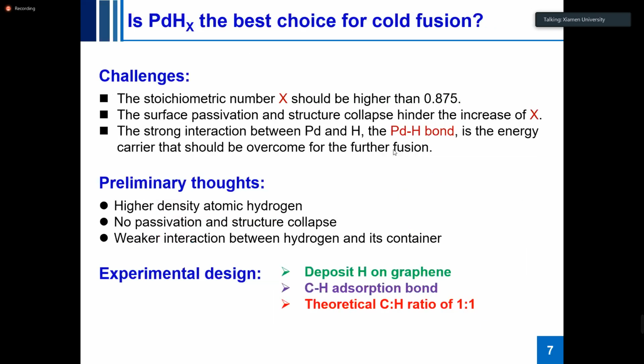So my question is: is palladium the best choice for cold fusion? I think the challenge comes from the following three domains. The stoichiometric number X should be higher than 0.875. This is very difficult because the structure instability, the surface passivation and the structure collapse hinder the increase of X, and also the strong interaction between palladium and hydrogen. That means the palladium hydrogen bond is the energy barrier that should be overcome for the further fusion.